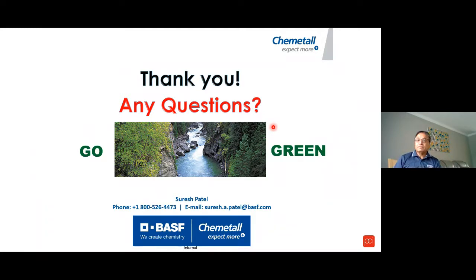How many rinse stages are recommended before and after the zirconium stage? Excellent question. So you can have one stage or you can have two stages. It depends again upon the size and the shape of your substrate. Depends upon how much potential drag out you may very well have. Depends upon whether you would have acid pickle stage between the cleaner as well as the zirconium pretreatment stage.